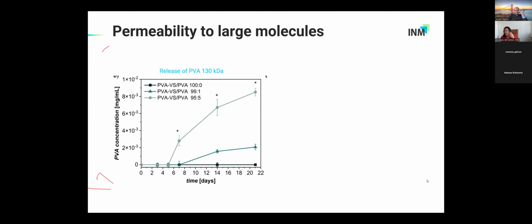Which additional properties do we need to check beyond the optical properties for our purposes? One is the permeability to molecules in any way, but in particular to large molecules. You will see later on why. And what we see is that the compositions that we are dealing with are permeable to large molecules. So here we are looking at the release of polyvinyl alcohol of 130 kilodaltons, and you see that it takes some time for the polyvinyl alcohol to diffuse through a hydrogel. In this case, this hydrogel is around 1 millimeter thick, but it does diffuse out, and it comes out from the other side. So we can actually release large molecules with these hydrogels, and small ones, of course, as well.